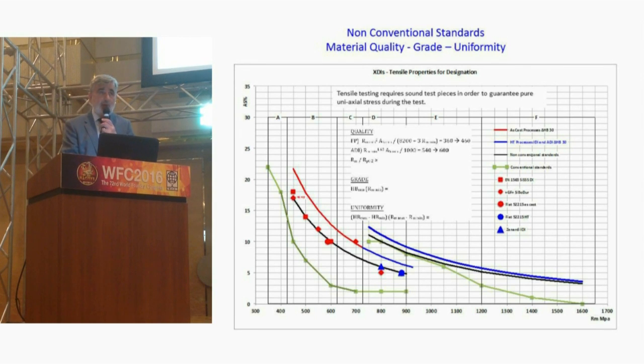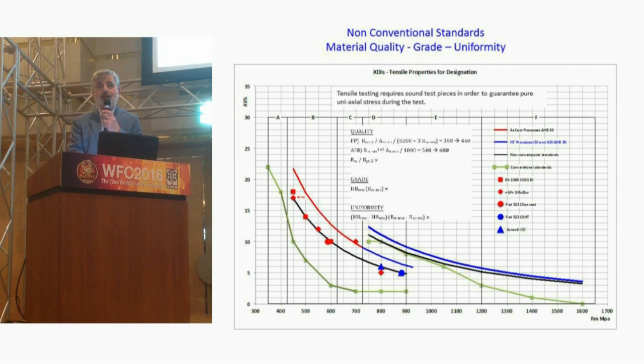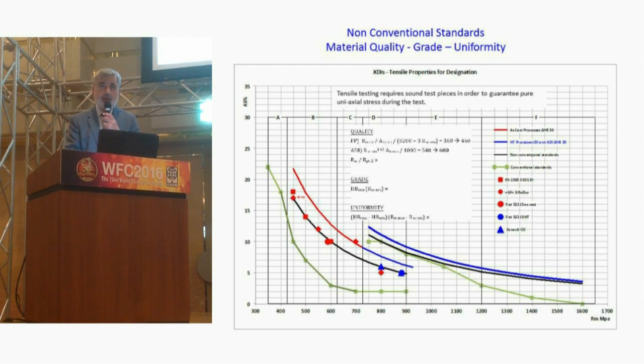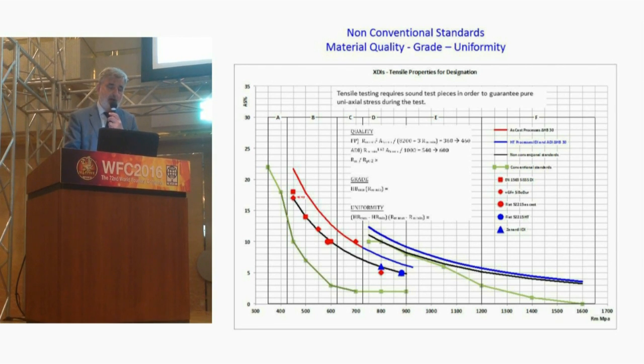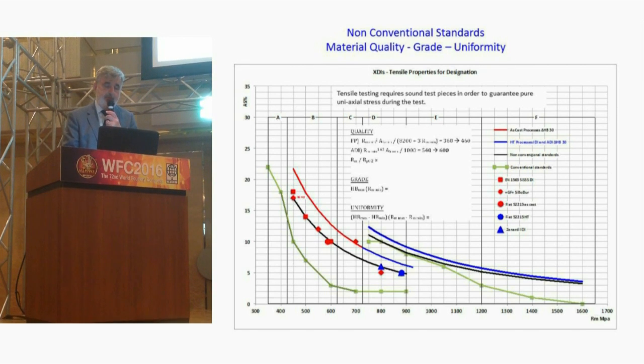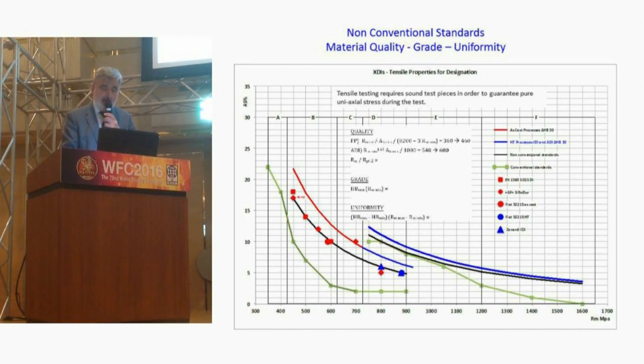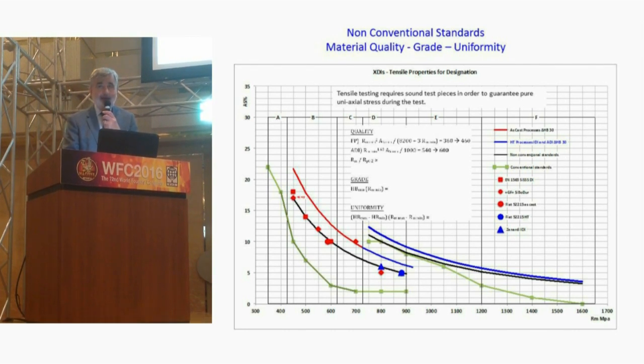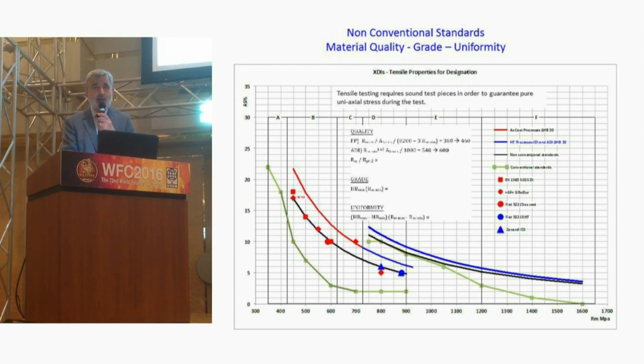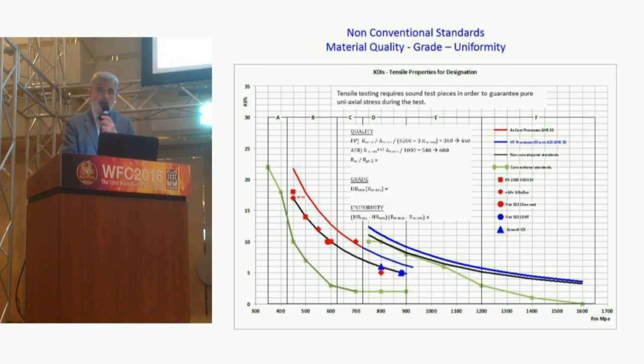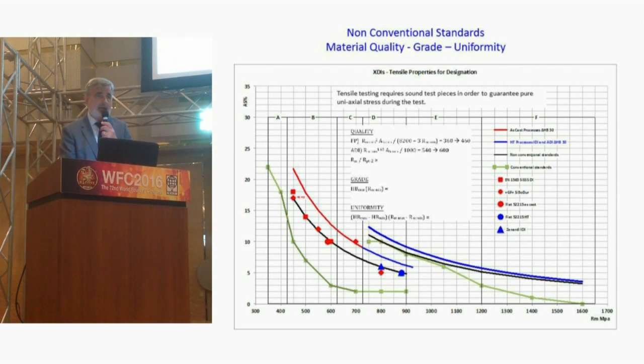And if we want to be allowed on our castings to have a Brinell hardness range of, for instance, 30 Brinell points, to be able to do that, our couple of A5 and Rm should be above the other line, the red one on the left, representing the cast material, and the blue line for DI and ADI representing the heat treated material. This line guarantees the ability to fulfill the minimum properties and to have a Brinell hardness range of around 30 Brinell points. So one way to specify the material is to use a quality index that is a combination of tensile strength and elongation that assures that you are in this region.